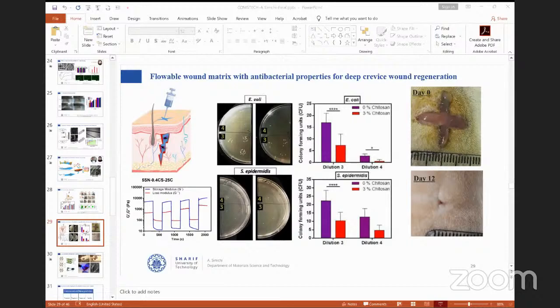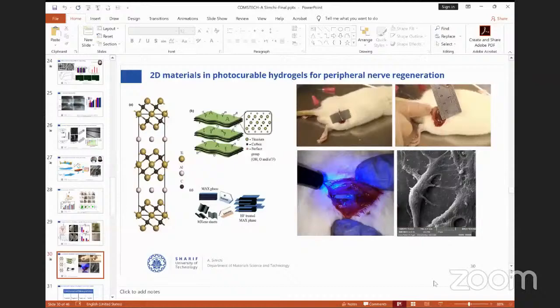On the right-hand side, you see the surface of the mice after deep injury, after 0 days and after 12 days. You see the injury after 12 days is almost fully repaired. It's an amazing result. It is not published yet. We are going to publish it very soon. But the result shows that this is an effective strategy to regenerate skin.